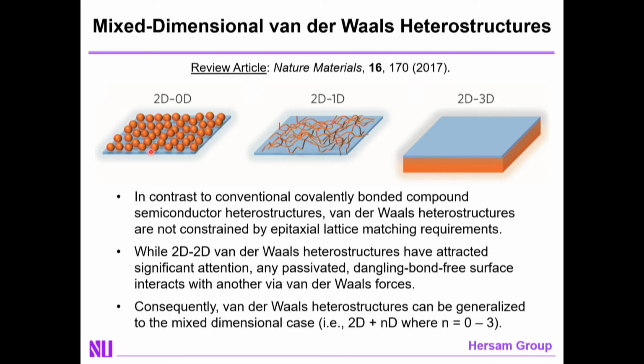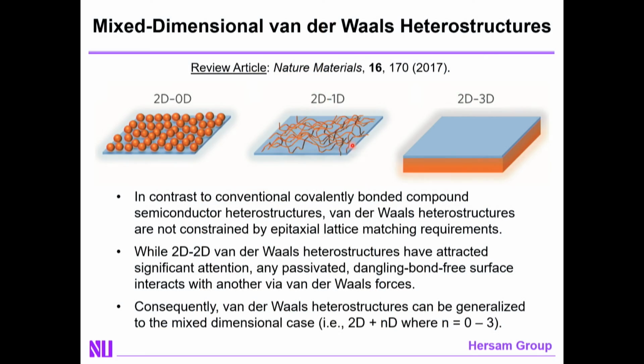And that not only increases the number of permutations for van der Waals heterostructures, but more fundamentally allows you, across an atomically sharp heterointerface, to qualitatively change the nature of the electronic density of states, to qualitatively change the degree of dielectric screening, to imagine excited states such as excitons, where the electron resides on one side of the heterojunction, the hole resides on the other side, and as a result, the composite wave function is neither one-dimensional nor two-dimensional, but truly mixed-dimensional in character. And of course, that will lead to new physics, new properties, and ultimately new applications.